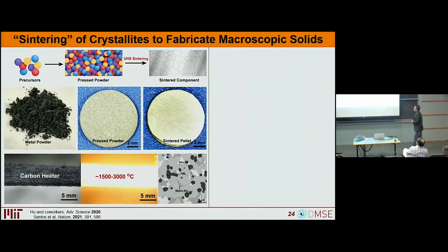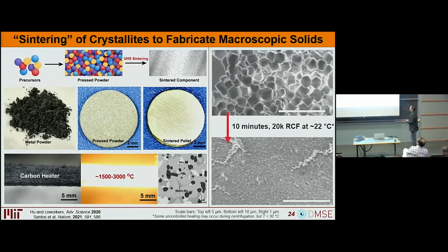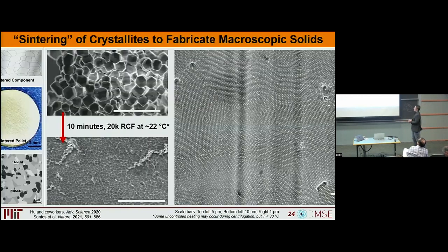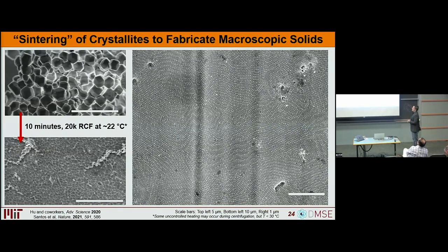So again, that same student I mentioned earlier, PJ Santos, he's not only a very clever polymer scientist, he's a good material scientist, and he realized that what we had with these NCTs was basically a powder. You can take a powder, and if you heat it and squeeze it, you can actually condense it into a bulk solid. So if we take these NCT crystallites and we simply centrifuge them at about 20,000 RCF at room temperature for about 10 minutes, sure enough, they densify into a bulk solid. But if we zoom in and look at it, all of that BCC ordering we started out with is maintained.